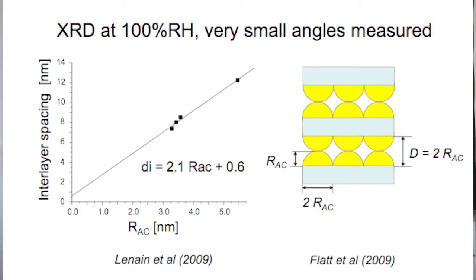So, another interesting result, which actually made me very happy, was that the student was still puzzled by these relatively narrow spacings that we were getting in the XRD diffraction. And so she said, oh, it might be the drying, so we got the samples equilibrated at 100% humidity, a couple of tricks to do the X-ray diffraction there, but also went to a place where she could do these measurements at small angles. And what happened is that we just realized, what I alluded to before, that the peaks that we've been looking at were just the harmonics of the main basal spacing. And that a normal XRD measurement will not be able to detect those very low angle peaks.